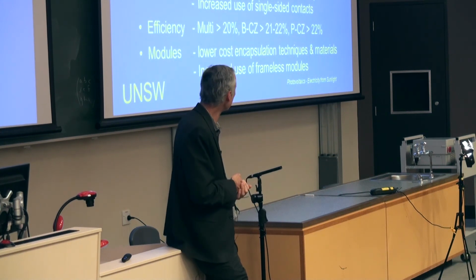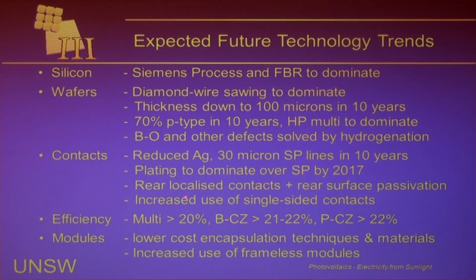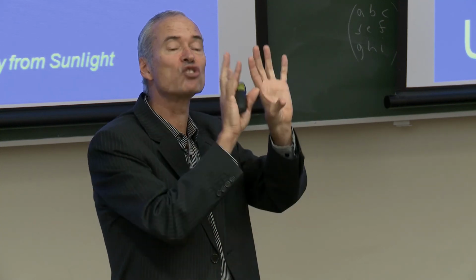Okay, then we're also finding some evolution in contact formation on the back. So at the moment, just about all solar cells have metal right across the back contacting the silicon. That's not the best way of doing it in the longer term, but it is the cheapest way and the simplest way, and that's how it's done at the moment. But as we move to higher and higher efficiency solar cells, it's going to be important that companies replace that rear design with one that uses a dielectric layer right across the back surface to passivate the back surface.